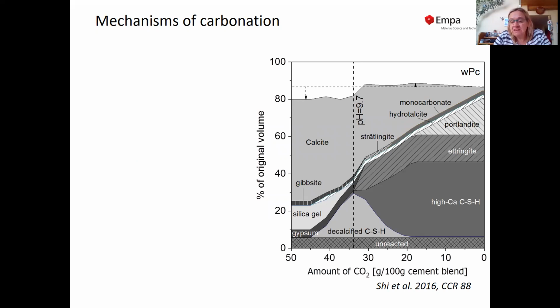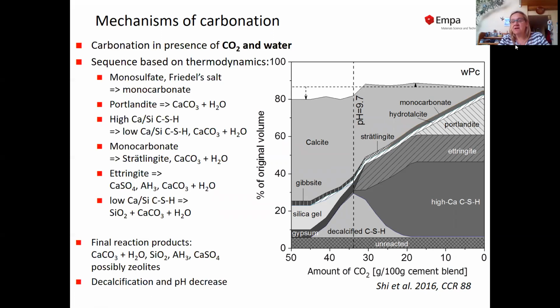Here we have to predict the composition of a hydrated cement in the absence and the presence of different amounts of CO2. And if we look first at the picture in the absence of any CO2, we predict, not unexpectedly, the presence of high calcium CSH, of ettringite, of portlandite, a minor amount of AFM phases and hydrotalcite, and also a little bit of calcite, because the original cement also contained some limestone.